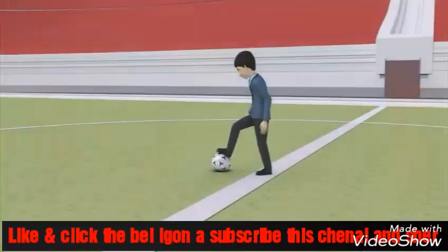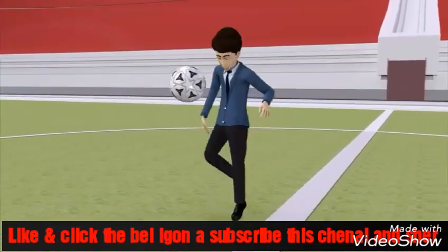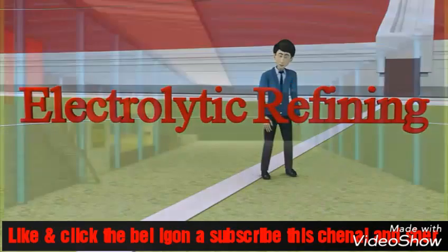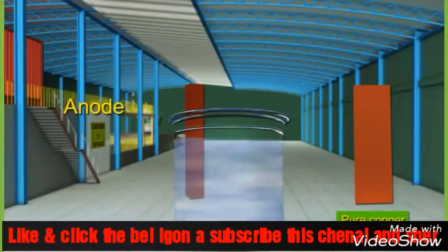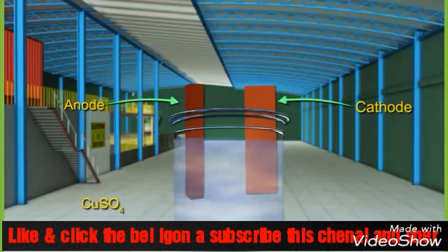It is purified by electrolytic refining. Take impure copper metal as anode and a thin plate of pure copper metal as cathode. Take copper sulfate solution acidified with sulfuric acid as electrolyte.